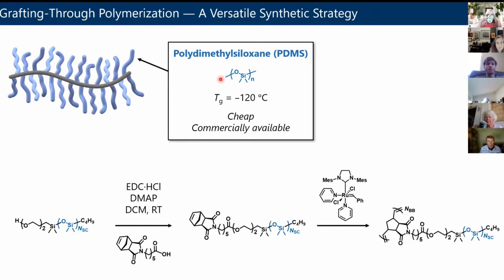And to get a flavor of how we do this from a synthetic perspective, we will buy a polydimethylsiloxane with a single reactive chain end, in this case an OH, and we'll couple that with a fairly complicated looking molecule, which is actually really easy to make, and it has a norbornene on one end. All of this other stuff is just a linker that allows us to couple it to that reactive hydroxyl group. So the important feature of this molecule is it has a norbornene connected to a polydimethylsiloxane. And then we dump in a little bit of the Grubbs catalyst and we polymerize that norbornene to build up a backbone. And you can follow this reaction by gel permeation chromatography.